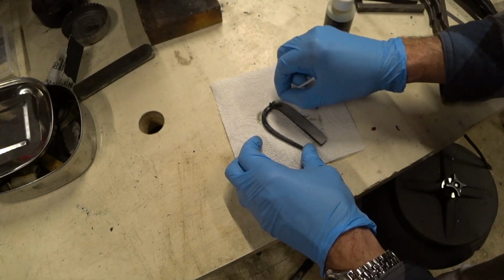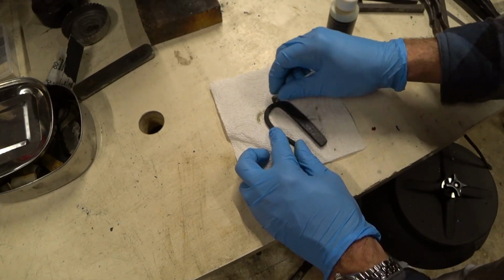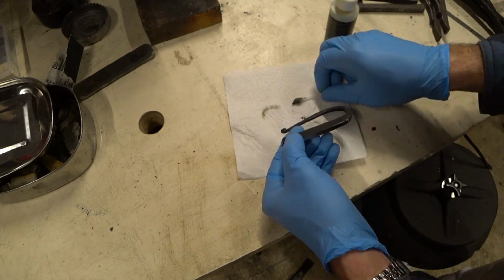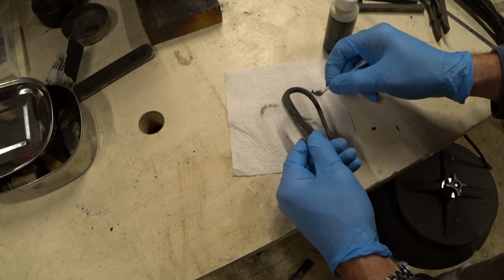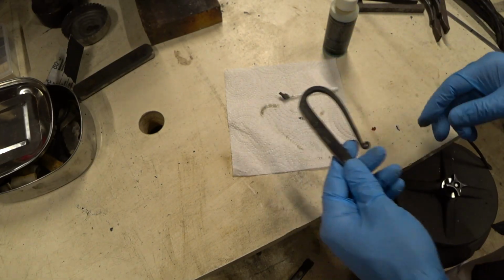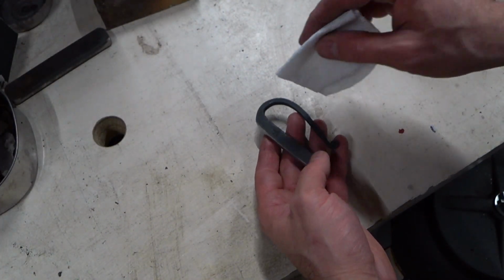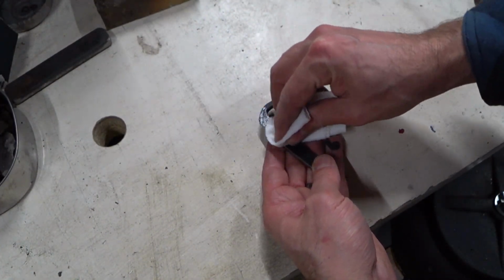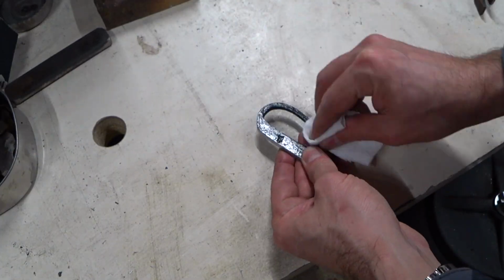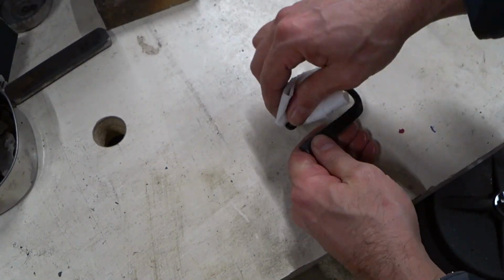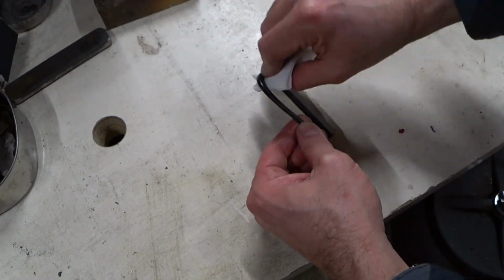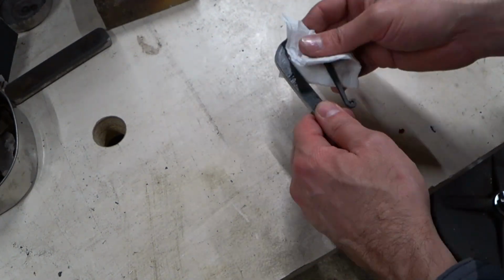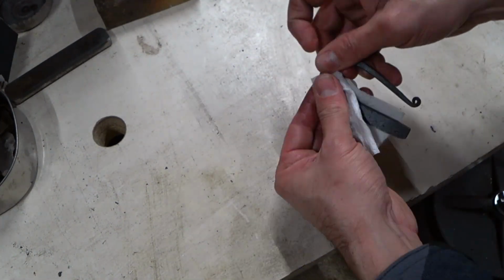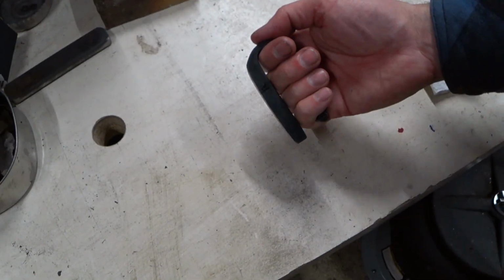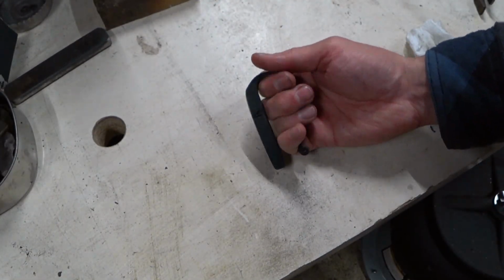You will get a black finish straight out of the quench just because of the oil that kind of polymerizes onto the steel, but I find that this is kind of ugly. It's not really uniform, so I usually like to clean it down to a bare finish and then use cold bluing in order to get the nice uniform black. After applying the cold blue, you want to wash off any residue and then apply oil or wax so that it doesn't rust.